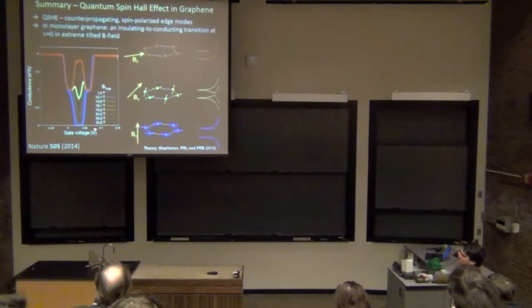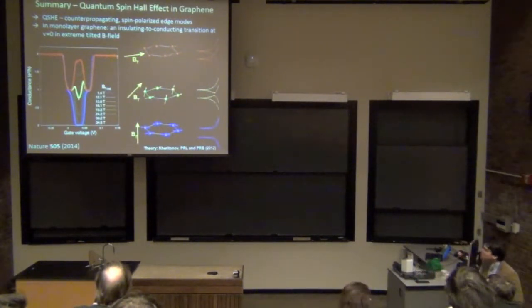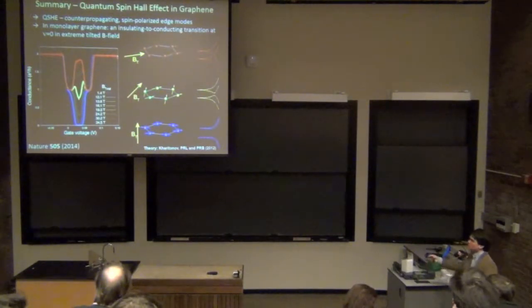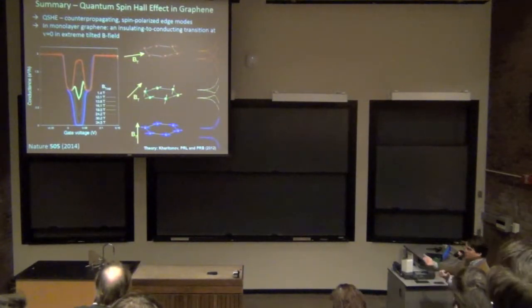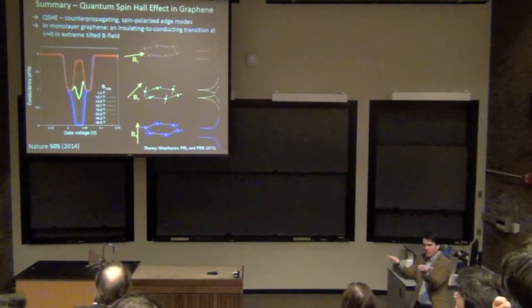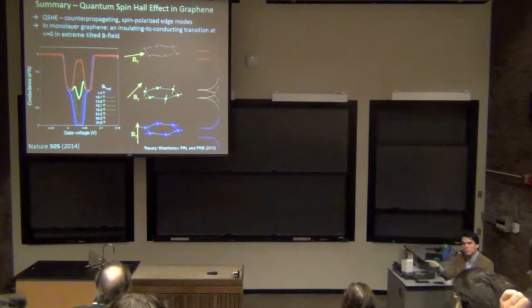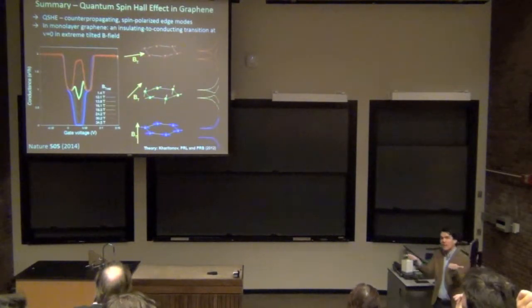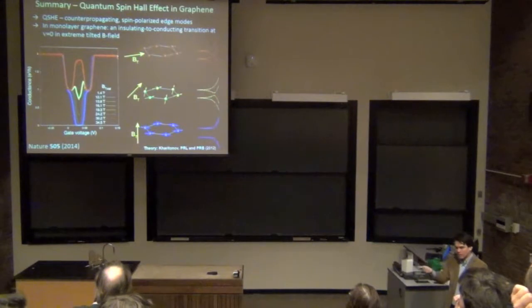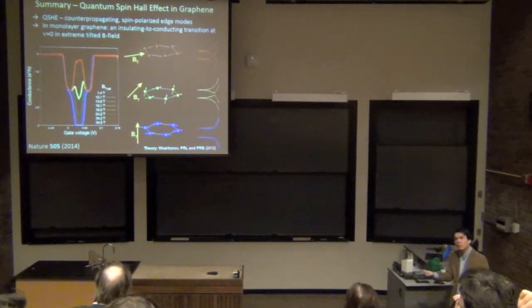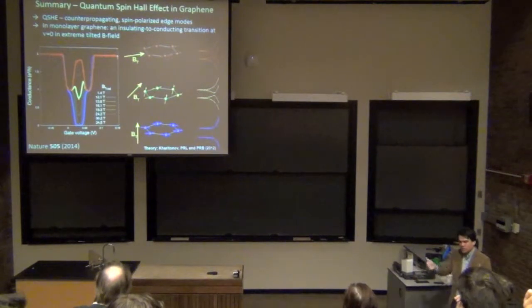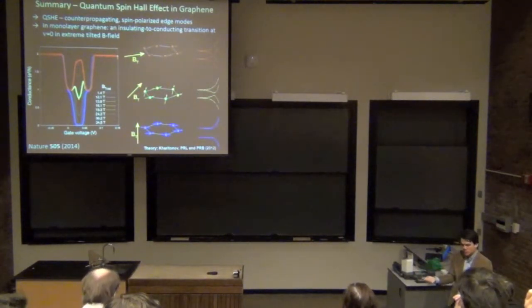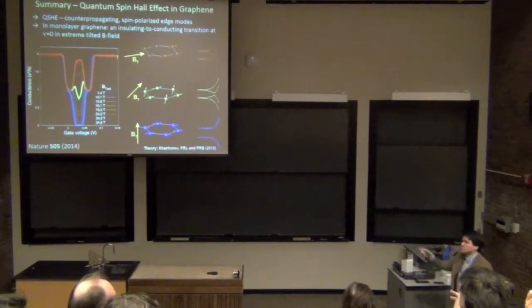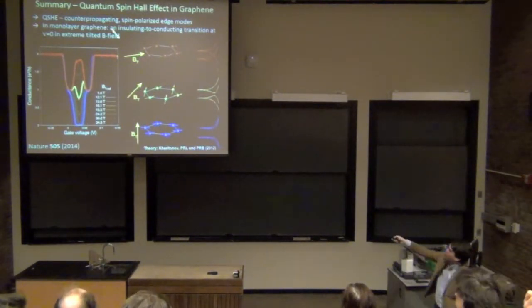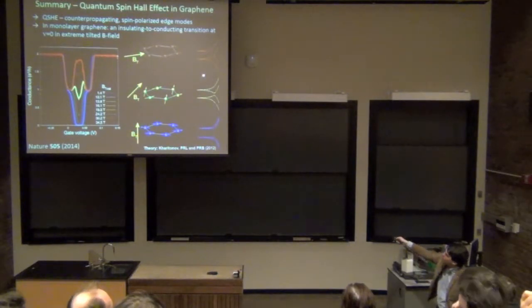So the states of the graphene are intimately related to what's actually happening in the bulk. The picture, which comes from the theory of Maxim Kharitonov, is that when we have the insulating state, the electron-electron interactions drive you to an antiferromagnetic state. Then when we use a huge magnetic field, the spins want to align with the field, so they start tilting in the direction of the magnetic field. But we're also tilting the sample at the same time, so the spin structure of the bulk looks like this, where all of the spins are pointing in the same direction.